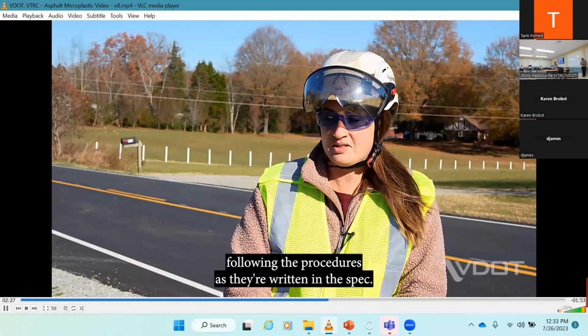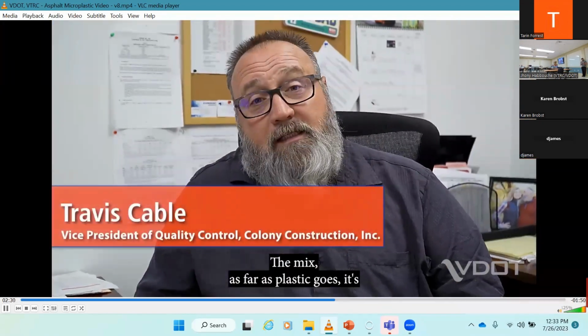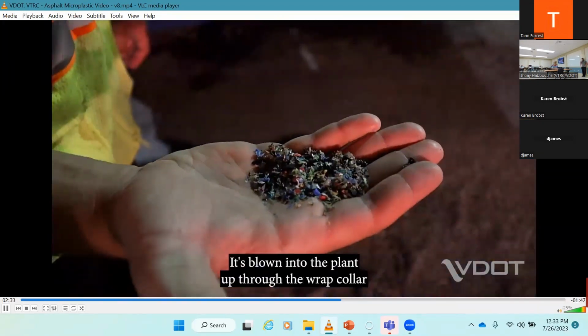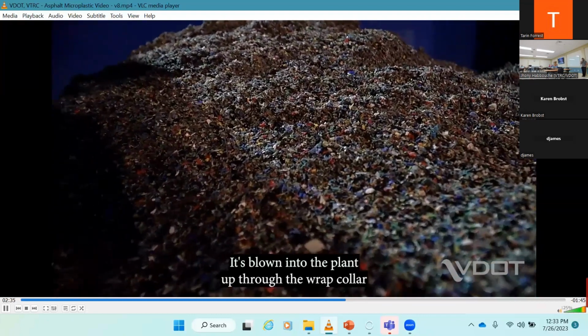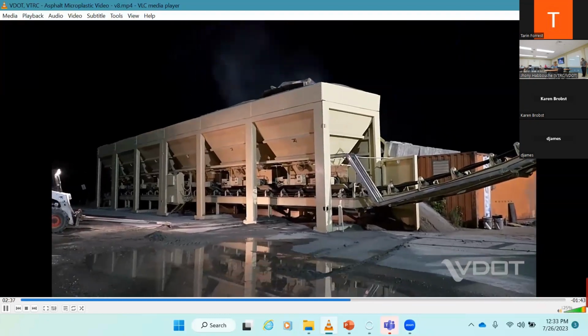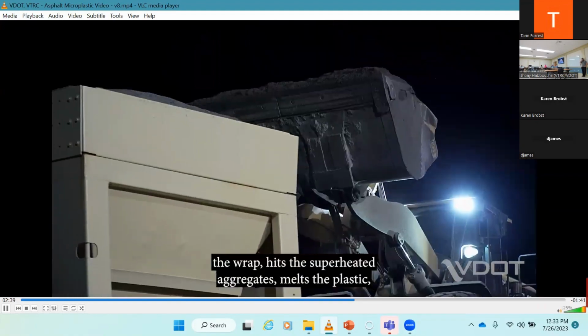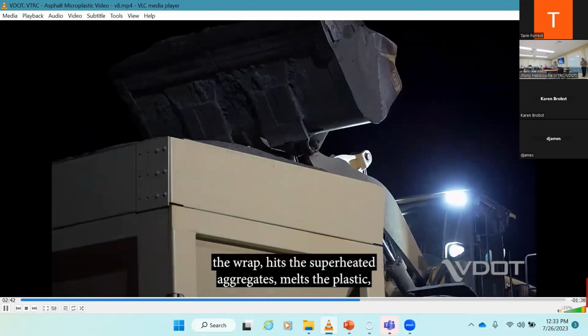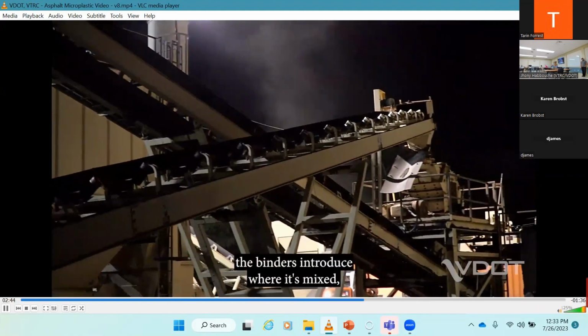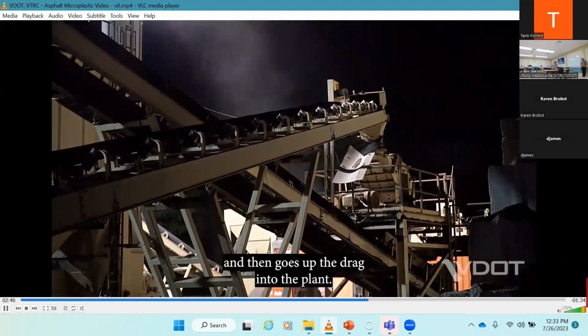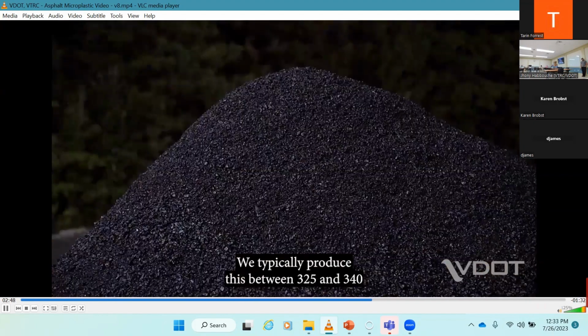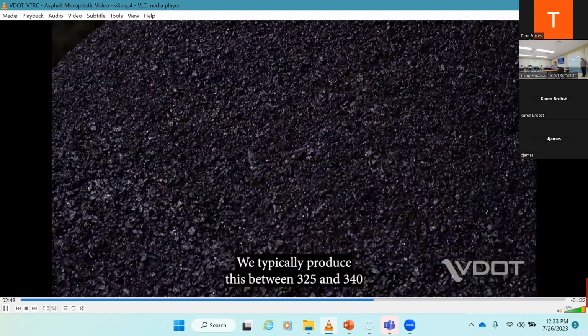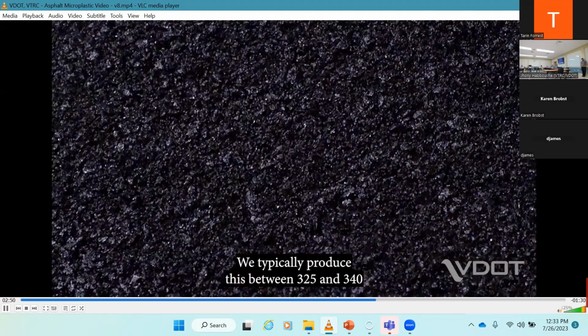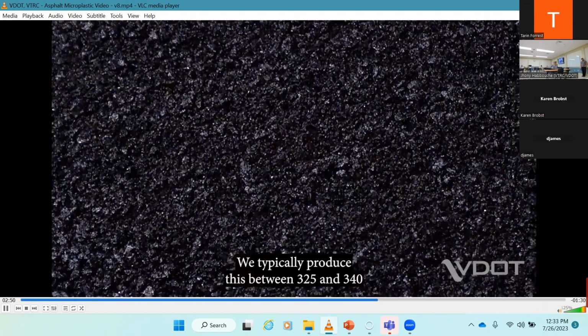The mix, as far as plastic goes, is introduced through a fiber machine. It's blown into the plant up through the wrap collar where it hits the wrap, it hits the superheated aggregates, and melts the plastic. The binder is introduced where it's mixed and then goes up the drag into the plant. We typically produce this between 325 and 340, and our lay down temperature is right around 300.